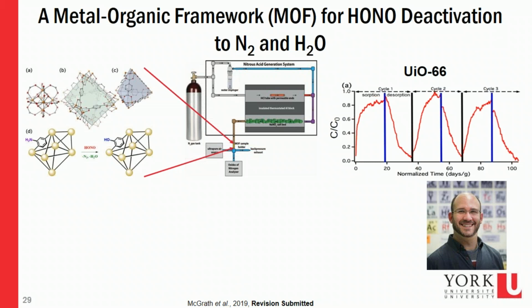When we take a metal organic framework that's based off of zirconium oxides linked with these particular linkers here with the hydroxyl on them, we can see that HONO will be sorbed onto the surface. So this is the concentration over the initial concentration of HONO. Then we modulate the MOF in line, and eventually the HONO will break through that MOF. Basically, all the surface sorption sites have been occupied, and the capacity for the MOF to retain HONO has been completely occupied. You turn off the HONO, you can then desorb it back out. So you can have a temporary storage of HONO inside of the metal organic framework, and you can turn it back on and off. So sorb and desorb reproducibly to sequester HONO, and then maybe take your MOF somewhere else and then flush it out is one approach.